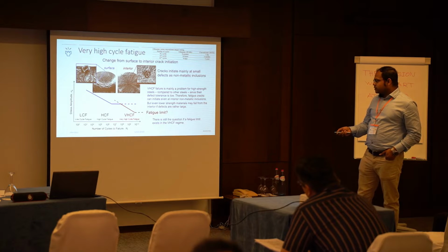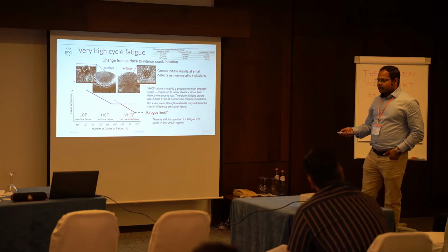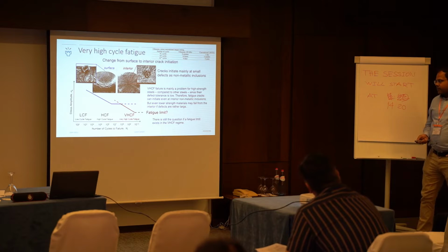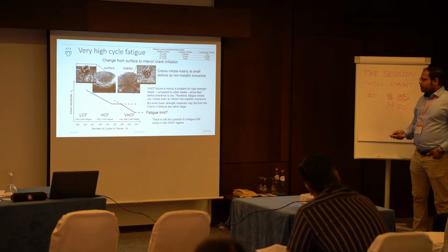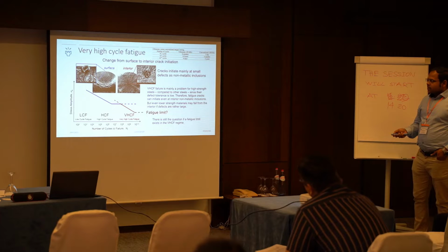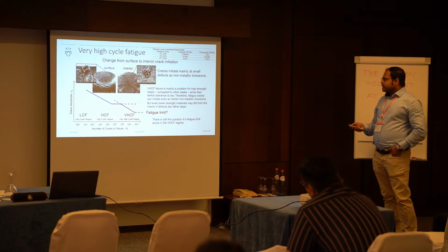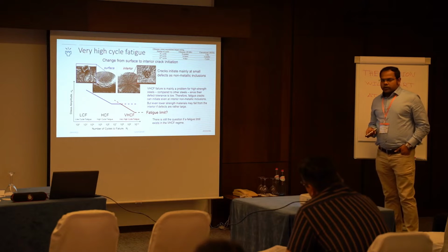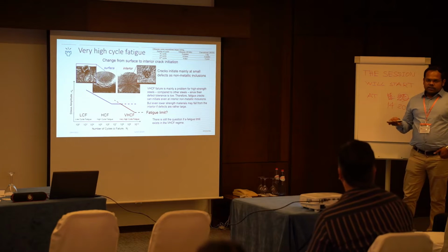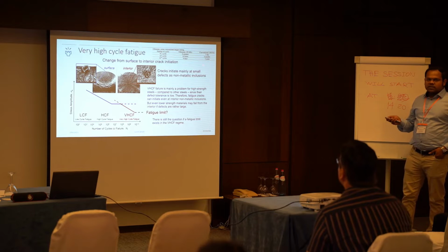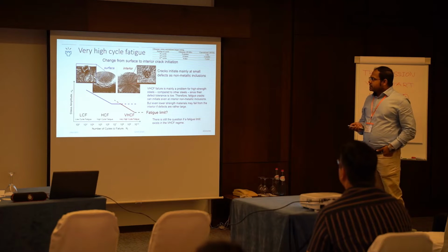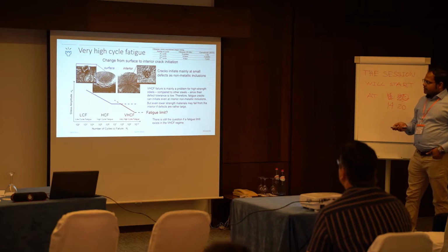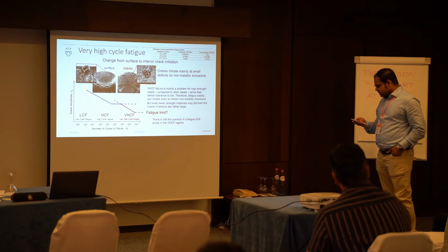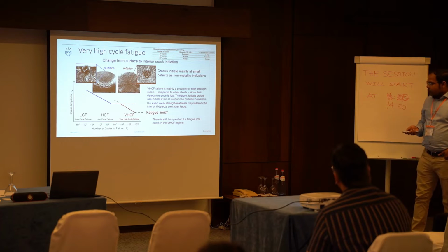So of course for that we would need to investigate more than 10^10 cycles, and you can imagine it's quite a time consuming job. If you think about conducting this kind of test using servo-hydraulic fatigue equipment, we know that we could apply a maximum of 100 Hz, and it would need 3 years to complete one particular condition. So thanks to the ultrasonic testing facility, we can attain 10^10 cycles within 6 days. So these are certain complexities. Now for